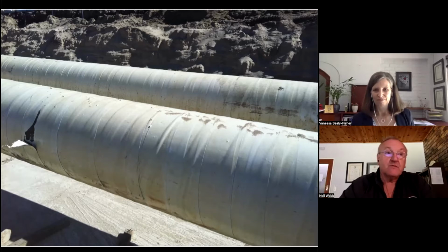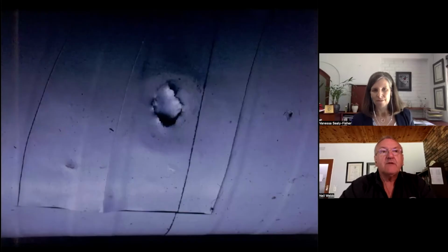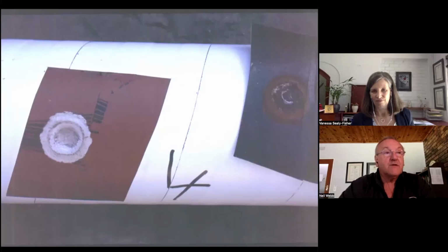One of the challenges with tapes, as with all the polyethylene, polyurethane, epoxy, all of these materials have similar electrical insulation properties. So if you even get a small defect, as you can see here, this is a little nick in a tape wrapping system caused by, in this case, sharp backfill because they did not use sand padding. And whilst that looks fairly innocuous, sitting underneath it was a significant level of bacterial corrosion.